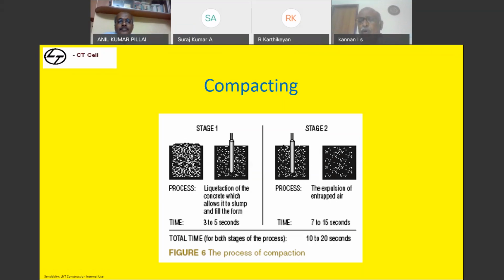In the continuing compaction, I keep on vibrating it. I push the needle up and down. When I am pushing up and down, the air bubbles will start coming out. When the air bubbles start coming out, you will be able to see the concrete revolving around the vibrator needle. When you see that, the compaction at that location is over, and you have to slowly withdraw. That needs hardly 7 to 15 seconds. That means as a whole, if I'm inserting a vibrator needle in a position, only 10 to 20 seconds is needed for compaction. This 10 to 20 seconds depends upon the type of slump. As I said, depending upon the workability, the compaction time needs to be checked.